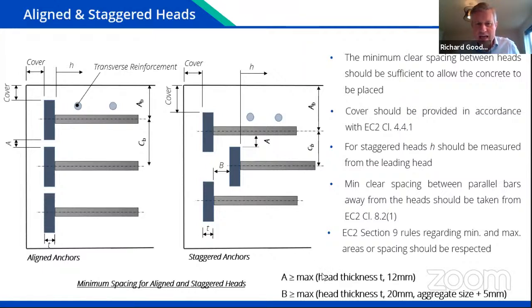So within the guide, we've given A as the maximum of the head thickness, or 12 millimeters, just again to allow for the successful placement and compaction of the concrete. And we've given B here as the maximum of the head thickness, 20 millimeters, or the aggregate size, and 5 millimeters. So this technique of effectively transferring the load from the head to rebar bond can be used all the way down to the minimum spacing requirements. But as you reduce your spacing between the heads, of course, it means that you need a greater and greater bond length.